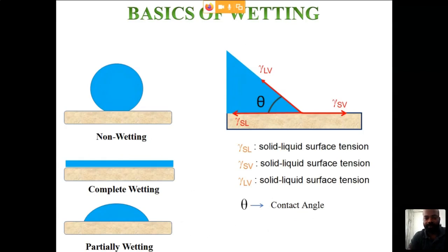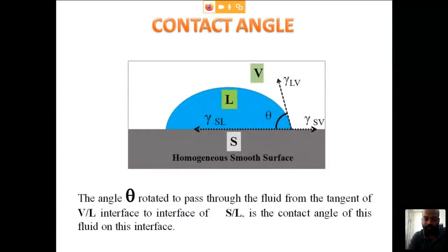The balance of the surface energy and surface tension plays a major role in deciding the wettability. Now, what is contact angle? If you take a droplet on a surface in an ideal condition, where the surface is perfectly smooth and homogeneous in terms of chemical composition, made up of only one kind of chemical, then the angle subtended at the three-phase contact line, where all three phases merge together, measured through the denser medium, the liquid, is the contact angle. It is not the opposite angle; the contact angle should always be measured along the denser medium. So it is the force balance between these three phases at the three-phase contact line.